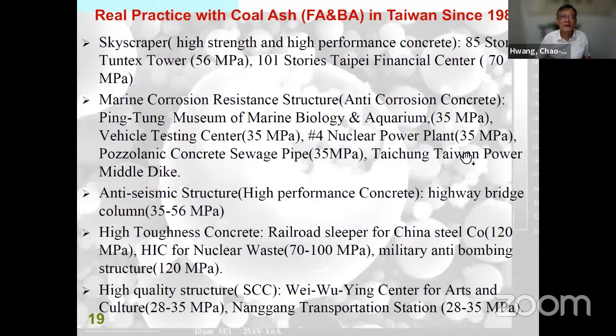It can consume calcium hydroxide from cement. That is a way corrosion is caused, because the water contains some sulfate. They will react with the cement and generate ettringite. So that will expand and cause corrosion. But what I'm doing is using a similar method from the Kaohsiung 85-story building, using that concrete, only certified for marine concrete. So Pingtung Museum of Marine Biology and Aquarium. So I designed this one from pile, from building and to the roof, all using this kind of concrete and